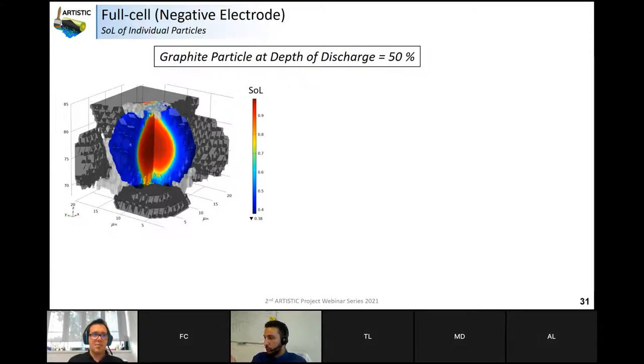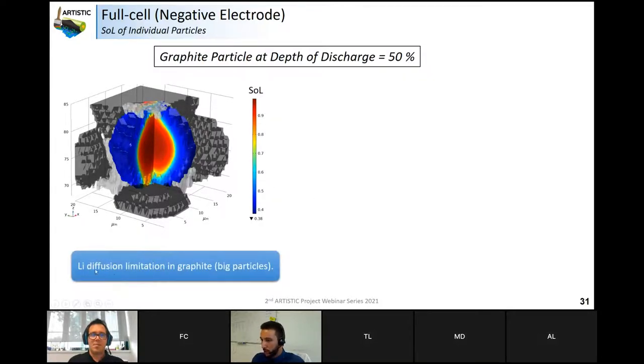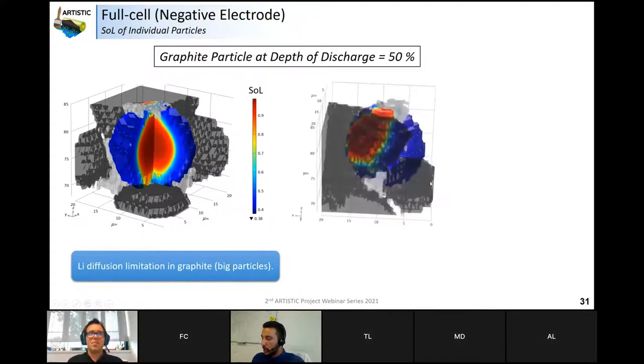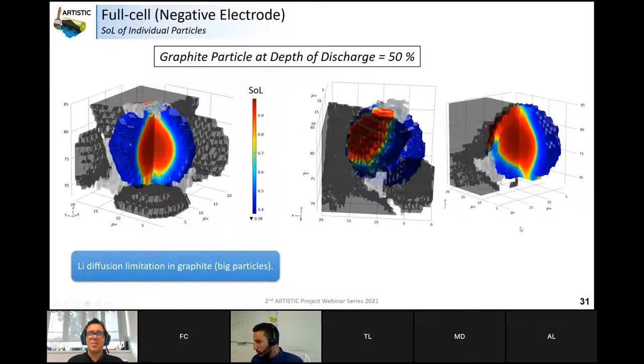So here's the case for graphite particles. You can see you have the lithiation profile. So like I said before, you have lithiation diffusion limited because of the size of your particles. And if you have a look at the environment, here you have also other active material particles that are covering the surface, preventing the lithiation to be delithiated. And also, it will create a non-homogeneous distribution, because since the particles are spherical, you might expect a spherical distribution inside, but it's not the case because of this environment of your particles.